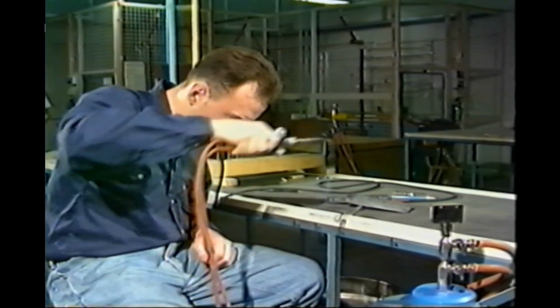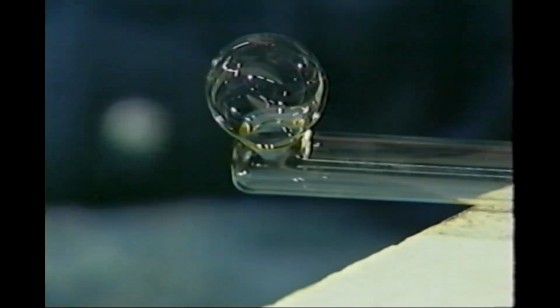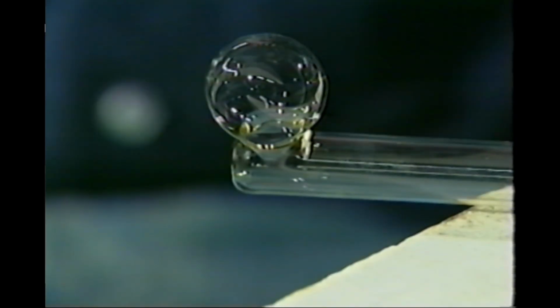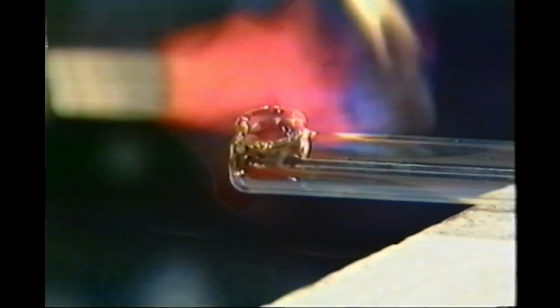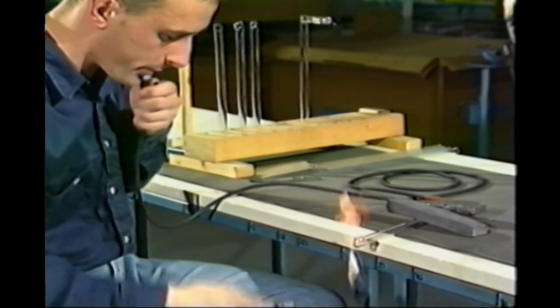Melt down the bubble again halfway down. Remove the flame and blow this time to form a large, thin bubble. Break this open with the tweezers, melt back the rough edges of the hole to leave a 15mm diameter hole with a flat, clean-edged shoulder. Anneal the butt end and hole and surrounding glass with a large soft flame.